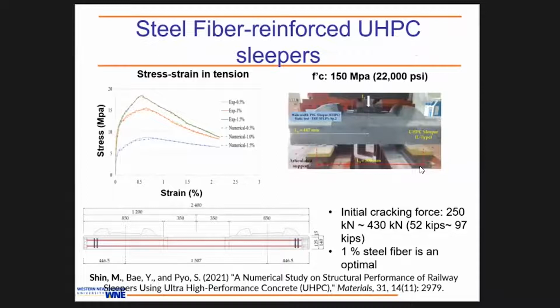In this UHPC with fibers, how much dosage of fibers do we need to add to achieve certain performances? Their study concluded that 1% steel fiber by volume of the concrete is the optimal dosage. The top left corner is the stress strain curve in tension of the concrete. That's a direct tension test.